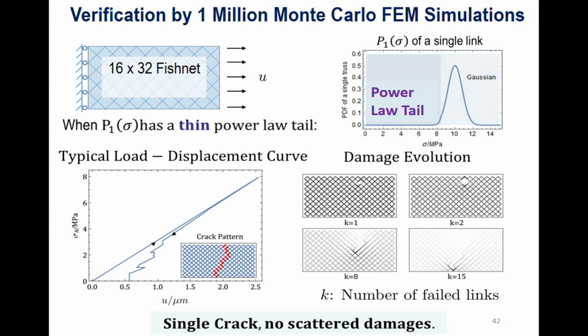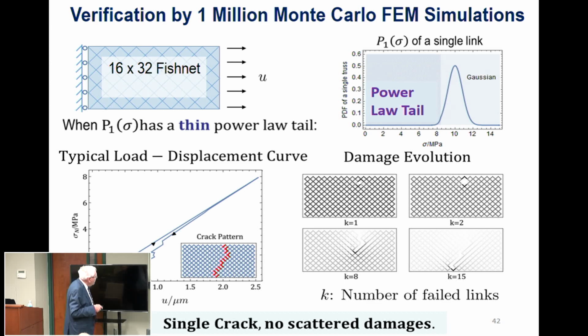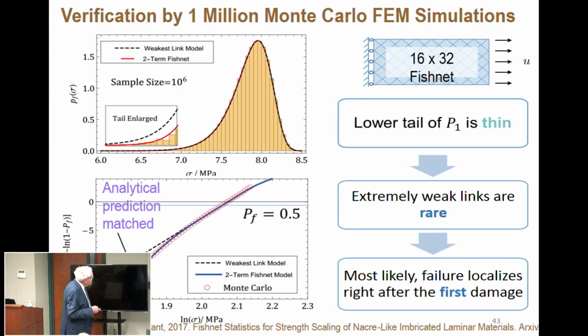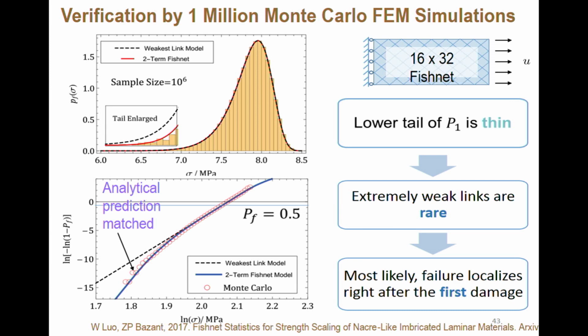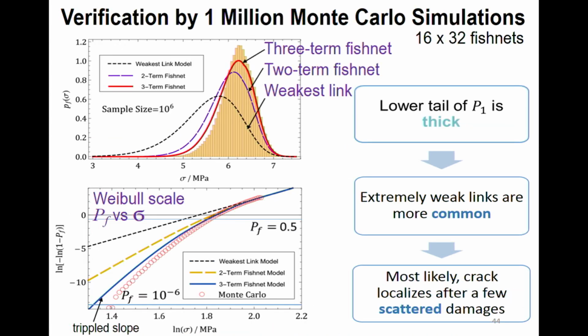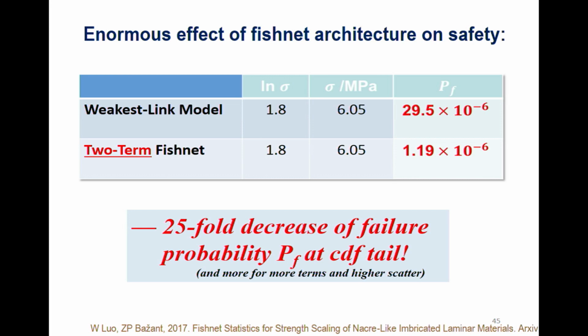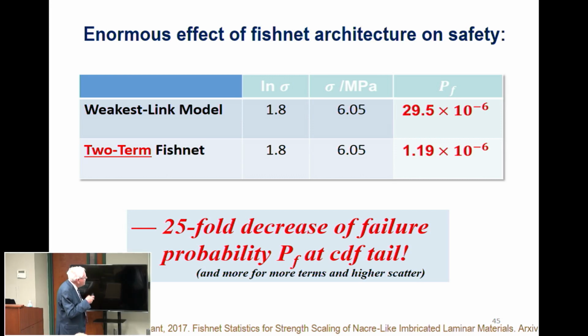All right, so here I show the distribution, the power law tail, the typical load displacement curve. This is the spread of damage from the simulations. This is the same thing in CDF, probability density function, the tail consideration. Again, analytical prediction compared. But let me point out now the gain in terms of probability. Before, I showed the gain of strength, probability being fixed at 10 power minus 6. Now in terms of probability, the conclusion is that with the 2-term fishnet you decrease the probability of failure 25 times. So an enormous contribution to the safety of the material, with 3 terms somewhat more.